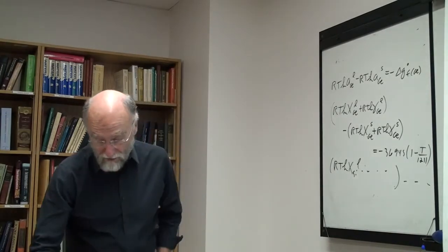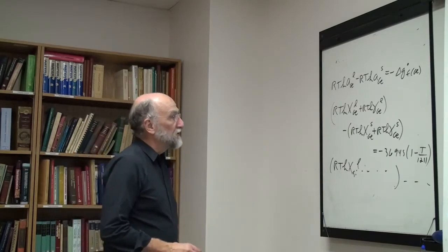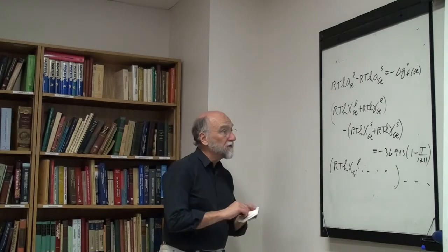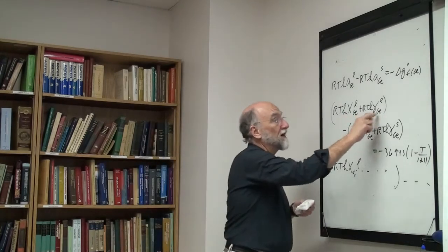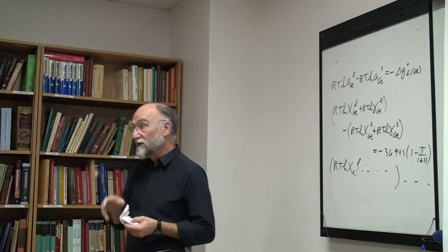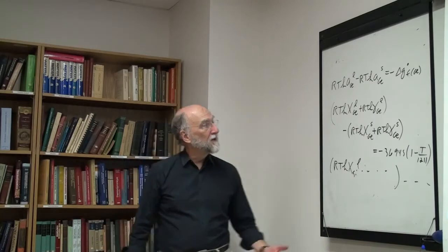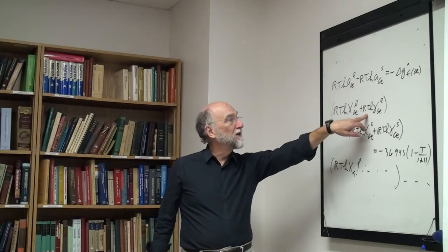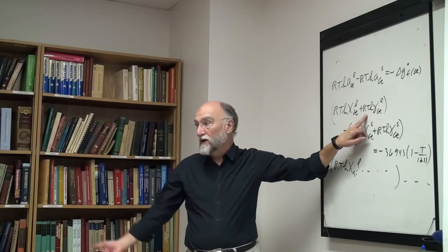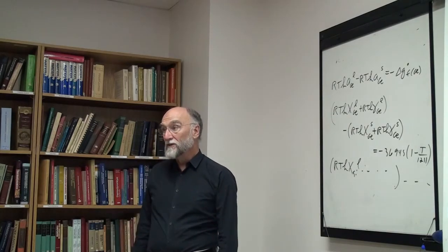Okay, so you have the two equations which you now have to solve. You have two equations, and three unknowns. Your activity coefficients are unknown, but they are functions of composition. So you could, for example, assume a regular solution, in which case RT log gamma of germanium would be equal to the mole fraction of silicon squared times a constant. In principle, the RT log gammas are functions of temperature and composition.